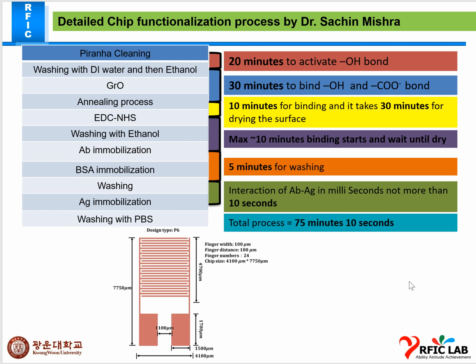So for the piranha up to the GRO it takes like 1 hour, and afterwards it's like 10 minutes for the EDC/NHS, and afterwards washing with the ethanol and antibody immobilization. And then BSA takes 5 minutes for washing, and then after washing with the PBS, the antigen is immobilized onto the surface, and it does not take more than 10 seconds. It's like milliseconds attachment between them, and this whole process is approximately 80 minutes, or like 75 minutes 10 seconds. So this is the whole process in terms of the timings.